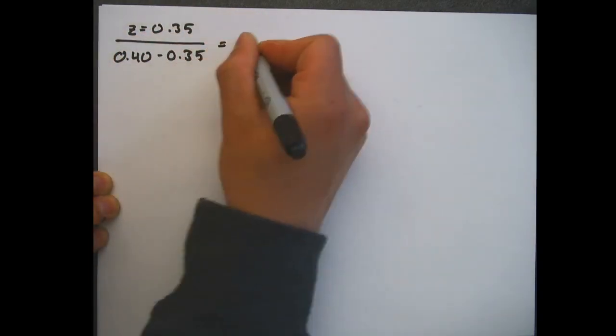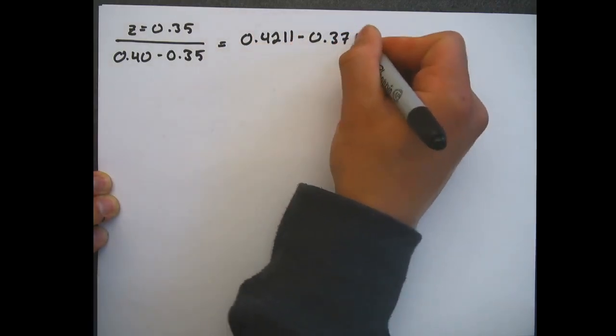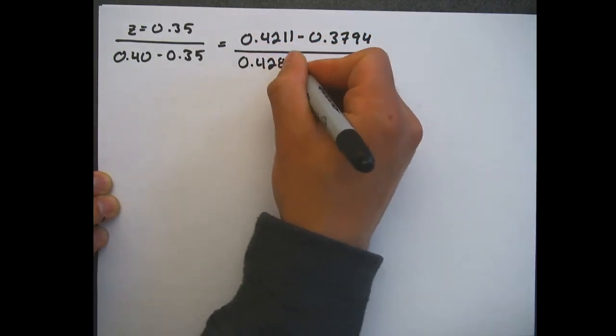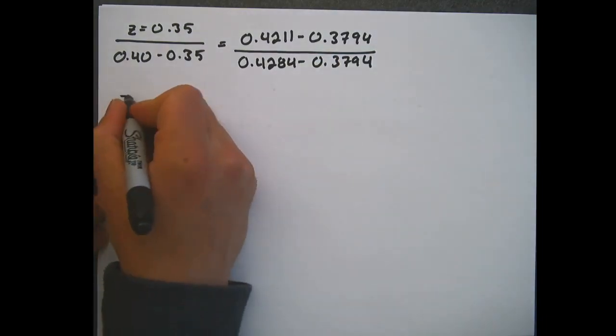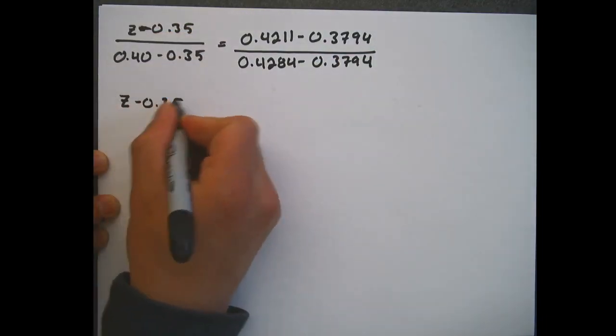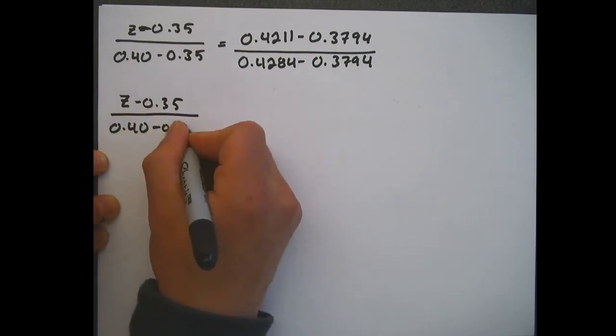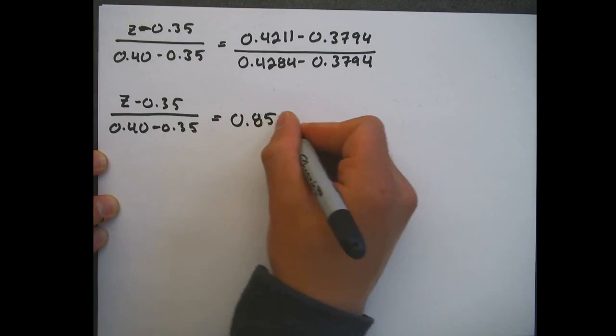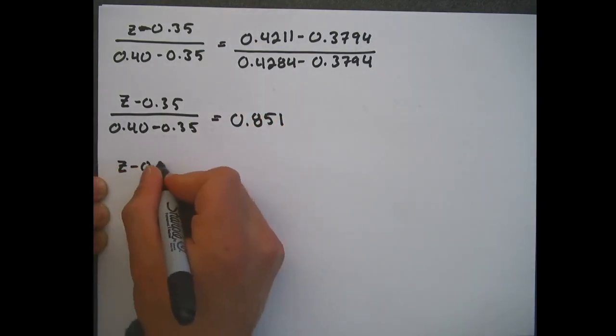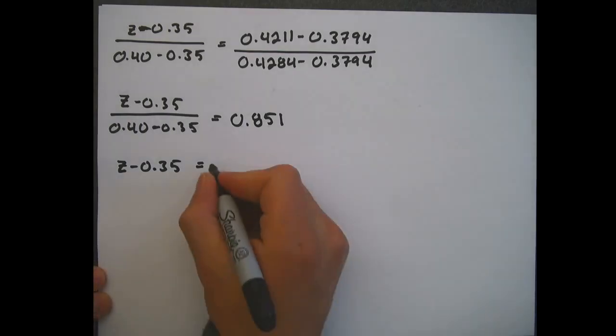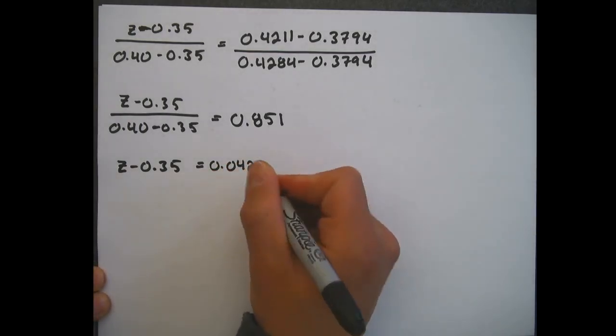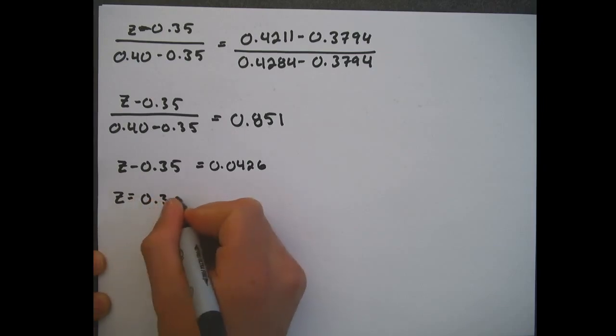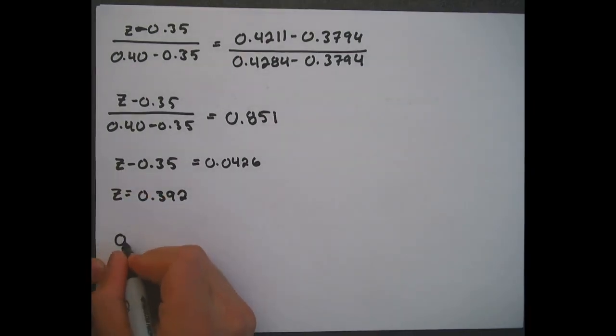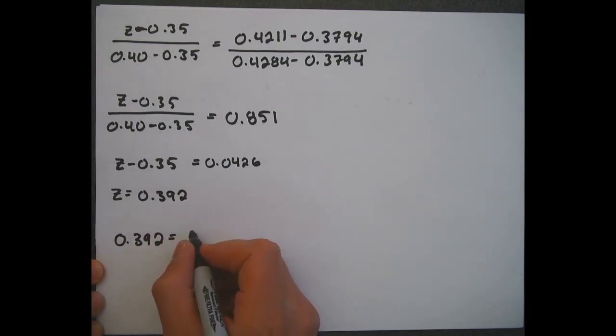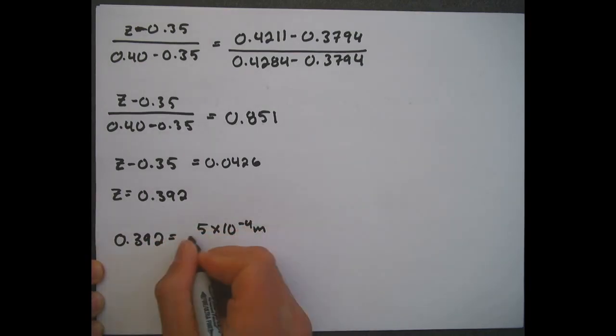After we have all of that written up, we solve for z. We already have our error function at z, so the only variable left is z. That is the equation shown earlier, just without the arrows this time. I solve the right hand side first and get a value of roughly 0.851. Now I get rid of the denominator by multiplying both sides, and I get 0.0426. So this means that z equals 0.392.